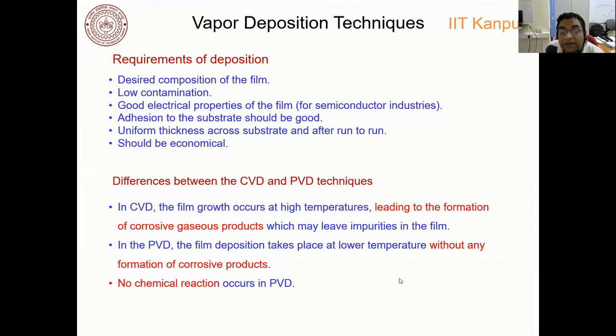In a physical vapor deposition, the film deposition takes place at relatively low temperature, but there are some variants as well when you require high temperature. But normally, this type of technique occurs at low temperature, and you do not form any type of corrosive products. Okay, so this is one of the advantages of PVD compared to chemical vapor deposition. In PVD, you do not form any type of products, and in CVD, you form gaseous products you have to flush out from the chamber. Now, this is one of the advantages, but then one of the distinct features of CVD is it has some chemical reaction involved, right? And in PVD, there is no chemical reaction involved. So this is a difference between a CVD and PVD process.